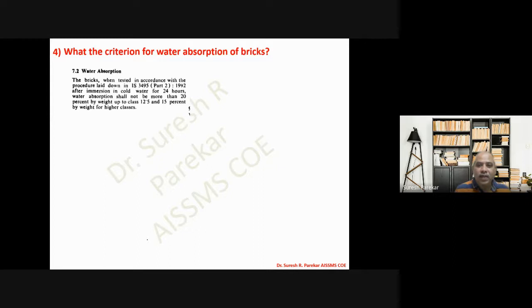Now, what is the criteria for water absorption? Once we get this value, the bricks when tested in accordance with the procedure laid down in IS 3495, Part 2, 1992, after immersion in cold water, water absorption shall not be more than 20% by weight up to class 12.5, and 15% by weight for higher classes. So we have seen we have these classes according to the compressive strength. We have 11 classes. Up to class 12.5 the water absorption allowed is 20%, and for higher classes, that is above class 12.5, it is 15% by weight. So this 12.5 is the compressive strength of the bricks, and the 11 classes we have already seen in compressive strength.